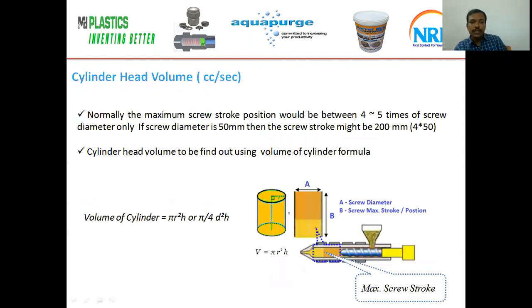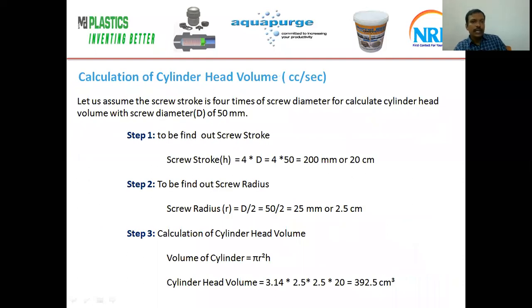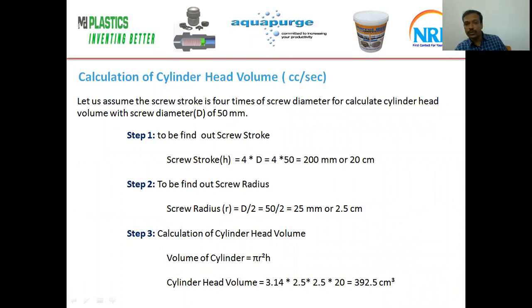Calculation of cylinder head volume. See, normally the maximum screw stroke in the injection molding machine would be 4 to 5 times the screw diameter. If the screw diameter is 50 mm, then the screw stroke might be 4 into 50 equal to 200 mm, 200 to 250 mm. Cylinder head volume we can find out using the volume of cylinder formula, such as pi r square h, or pi by 4 d square h. Let us assume the screw stroke is 4 times the screw diameter to calculate the cylinder head volume. 4 into 50 equal to 200 mm or 20 centimeters.